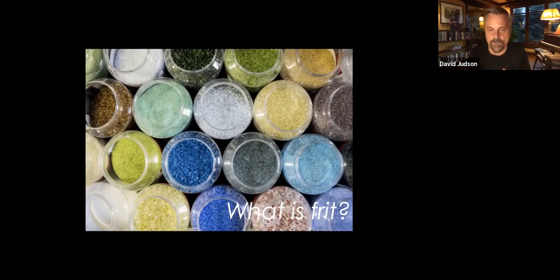So if we look at the traditional glass, that flash glass, for example, that I was telling you about, if you took 2 different colors and put them in a kiln and fused them together, they would break over time because they're not compatible. It's the mineral oxides of the colors in the glass that create the color. And those have different points of expansion. And so when the temperature changes or things shift, they stress each other out and break. But Bullseye created a glass that was all compatible. So all of the colors are compatible to combine together in a kiln and fuse together.